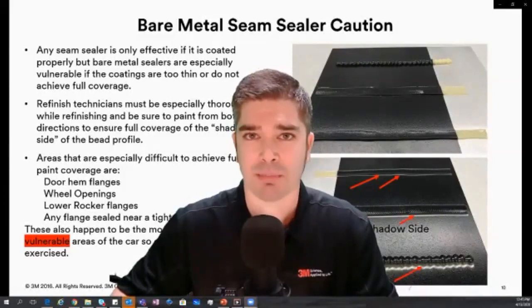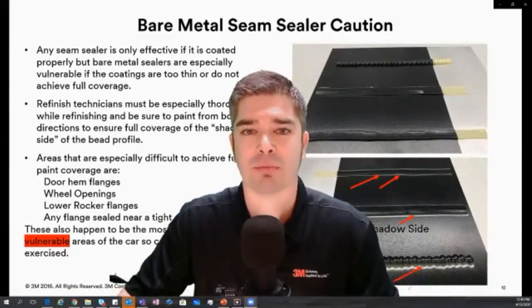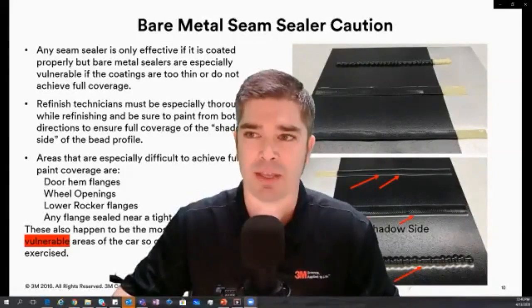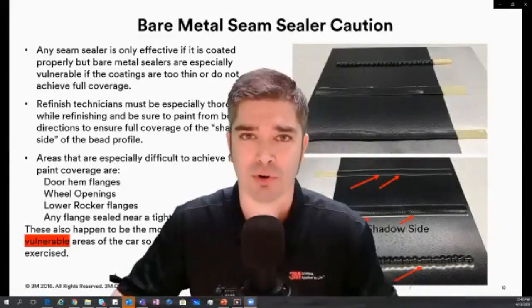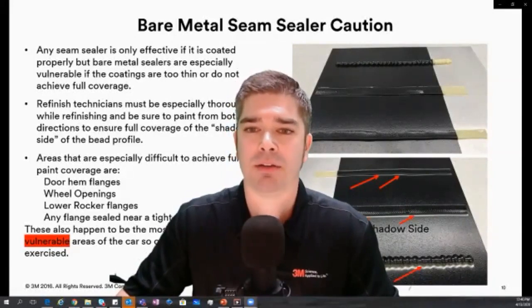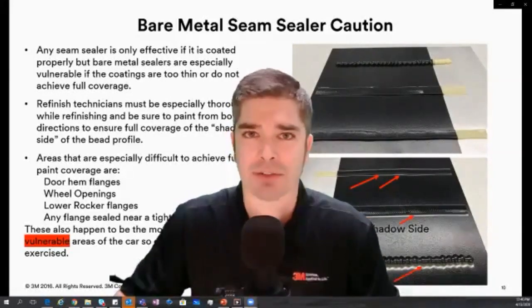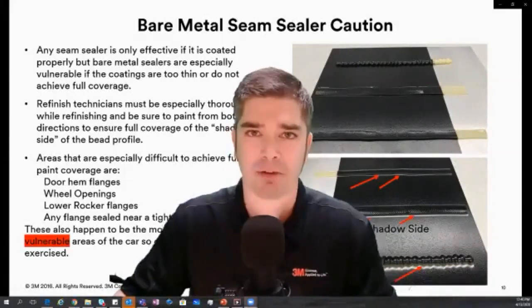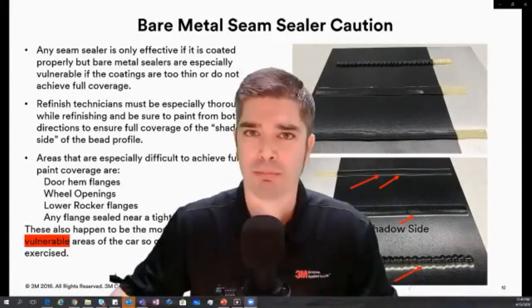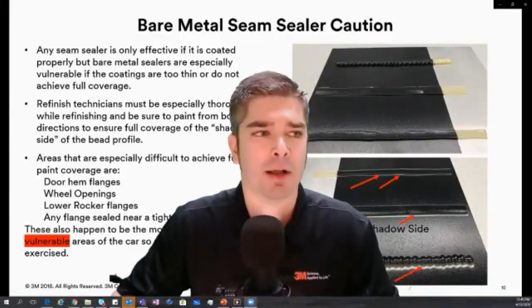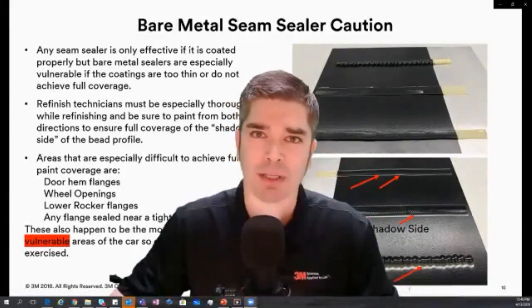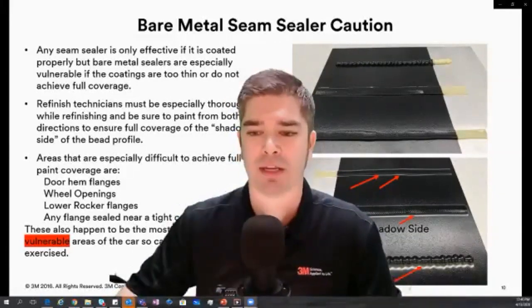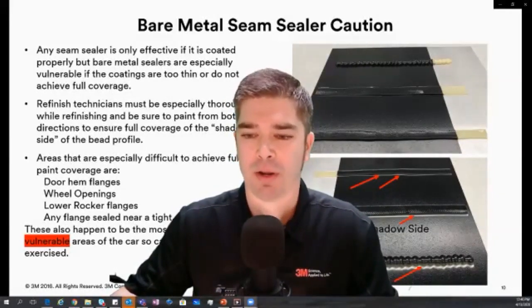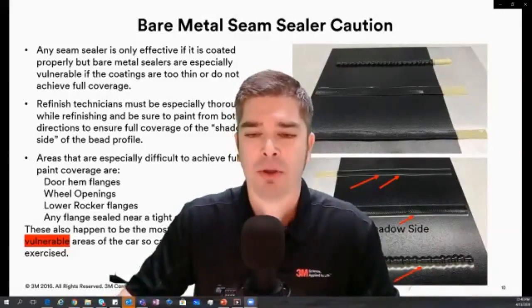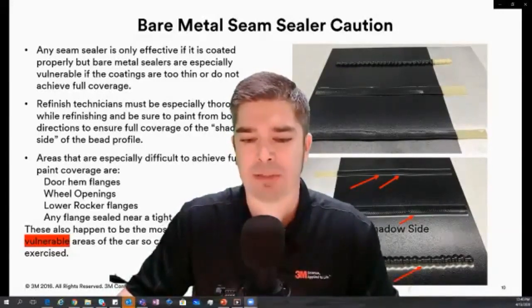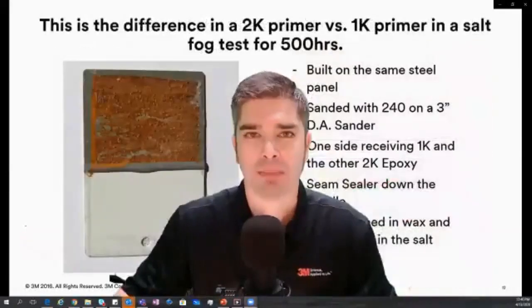appropriate 2K epoxy primer. And I point out 2K because quite often we'll see a technician saying, well, I don't put anything on bare metal because I've listened to your message, but I need it to be faster. So I'm using a one component, a rattle can primer. There's several brands and colors on the market, and they tend to get used because they're extremely fast, right? Again, we're in a fast-paced society where everything needs to be done right now, but sometimes that need for everything getting done right now doesn't mean that we're always making the best repair.